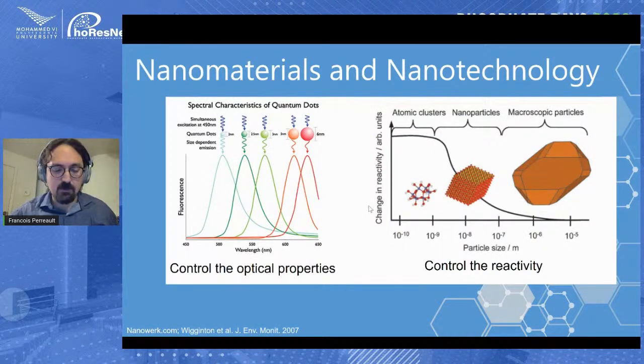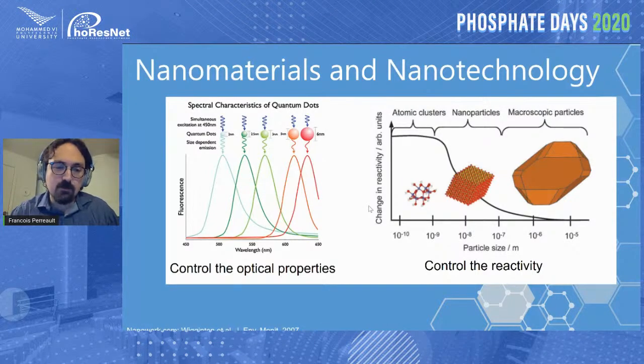So examples of these types of applications that we can be looking at are two very classical properties that we've seen in nanotechnology. The first one is optical property. This is what you have on the left. You can see the fluorescence emission spectra for different types of quantum dots, which are very small inorganic nanoparticles. And you can see that a very small change in size in these nanomaterials, less than 1 nanometer, 0.5 nanometer, can lead to a very significant shift in the optical property of your particle. And so material scientists in nanotechnology seek to exploit these small changes in size to tailor the optical property, the physical-chemical property of the material, to match exactly what is needed for the application.